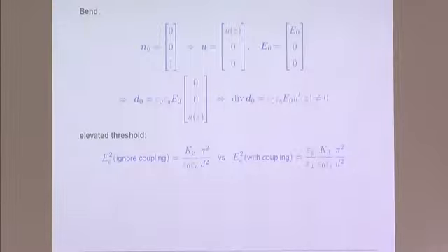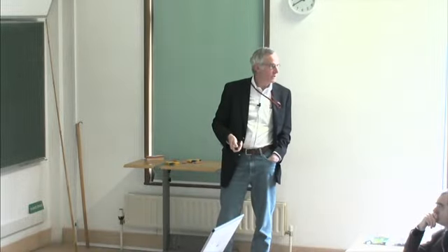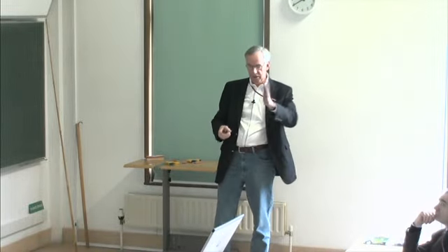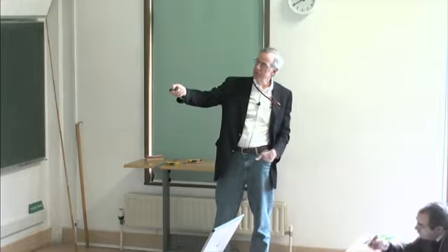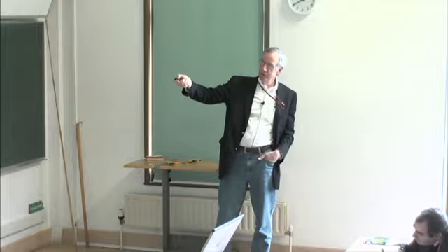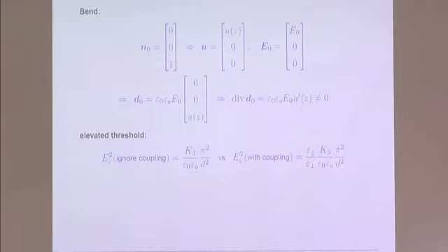In fact, if you carefully do the analysis of the electric field threshold, it's different than the simple magnetic field analogy. If you take the magnetic field version of this transition and just change the variables to the electric field counterparts, you would get this. But if you carefully do the coupled stability analysis, taking into account the coupling between the director field and the electric field, you pick up an additional multiplicative factor of epsilon parallel over epsilon perp in front.